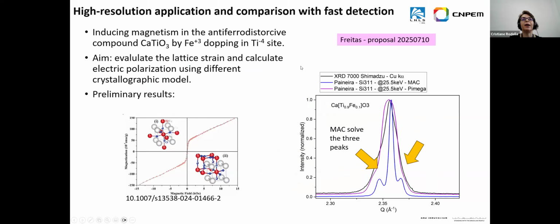Another one came from a user of the Paineira beamline. The group is studying this type of perovskite material, and they are doping this material with iron, and they want to know if the doping was exchanging the titanium site. If it was, they would have these 3 crystalline peaks here. But using a regular diffractometer, they just obtained this large peak, so it wasn't possible to confirm whether this doping was going in as a substitution in the sample composition or not. So they sent a proposal to the Paineira beamline and got the XRD pattern.